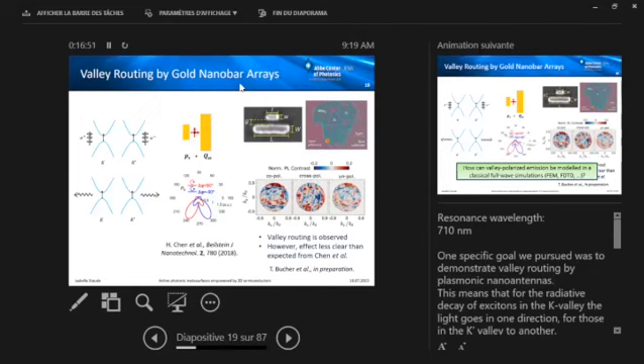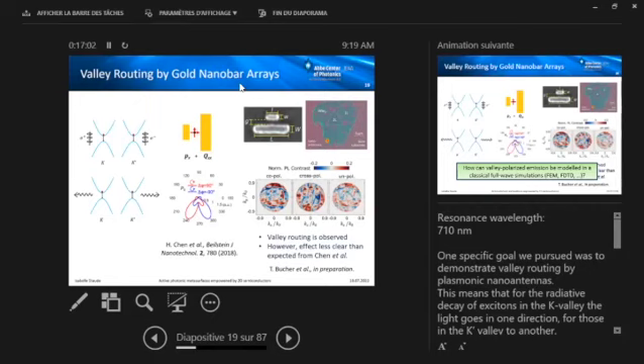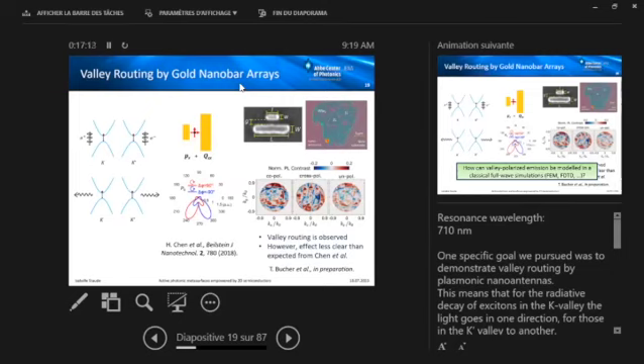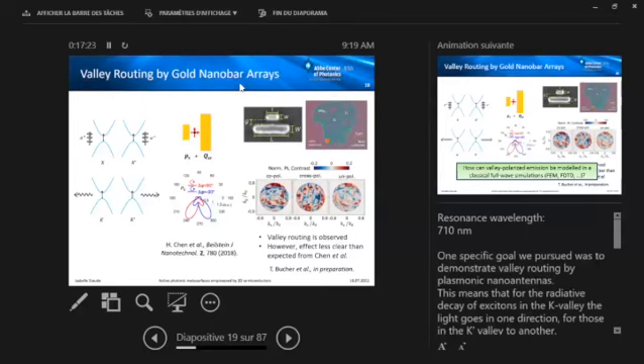So, we were inspired by this work by Chen et al. from ANU, where this multipolar gold nanobar antenna was designed using a spinning electric dipole as the light source here in the center. And depending on the sense of rotation, the light was going in different directions. So, we implemented this together with the Dragomir Neshev group in Australia, experimentally. And basically looked at the valley contrast. So, the nice thing is that we now have a very small system with a small footprint, but which we can still produce with top-down techniques. And also, in our experiments, we took a lot of care for really controlling both the excitation and detection polarization, because only this allows us to really separate simple spin-momentum locking effects in the system from true valley coupling effects.